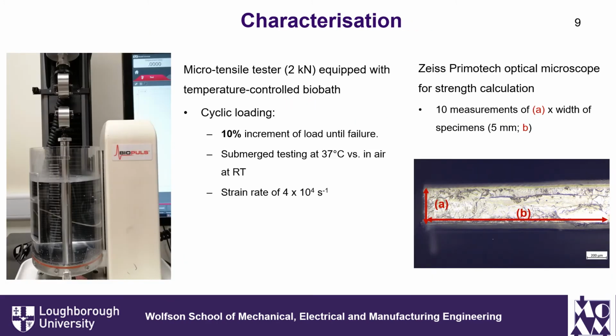Once we printed the boxes, we'll cut them and then characterize them accordingly. So for characterization, we use a micro-tensile tester equipped with the temperature-controlled bio bath, as shown on the figure on the left hand side. And for cyclic loading condition, we use 10% increment of load until failure at a strain rate of 4 times 10 to the power of 4 per second.